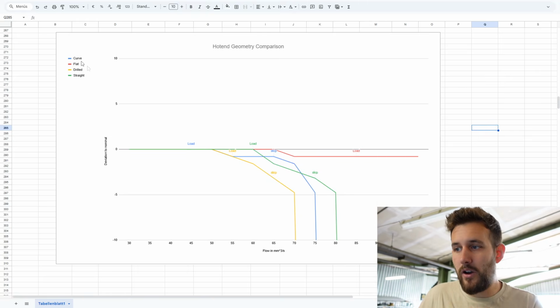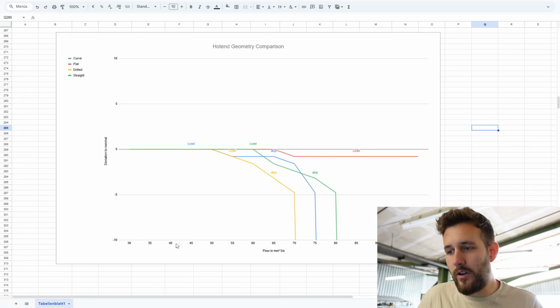So let's start with the curve section. And I could see right away from the very first flow test of 30 to 40 or whatever, there was a significant load on the system itself. Everything was a bit shaky and you kind of just feel that the extruder was working way more than before. And that showed in it already skipping at like 65 cubes of filament flow. So this is clearly not the way we want to go.